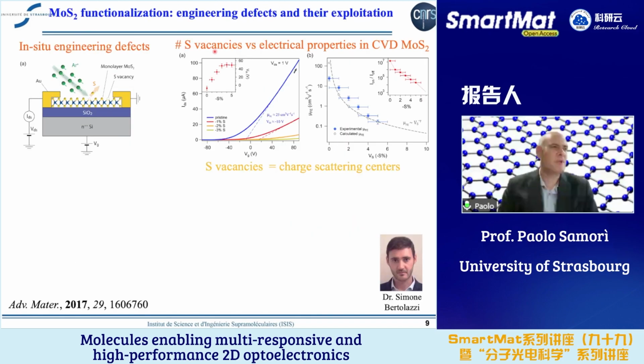Now, this is what we demonstrated in 2017 with Simone Bertolazzi in a study where we took simply molybdenum disulfide, which can be CVD, can be Scotch tape, and actually typically already in the pristine MoS2, every 10 by 10 nanometer, you have a point defect that is a sulfur vacancy. Well, this might not be enough. You might look for more defects, more vacancies, so by using some well-known approaches, we exploited the ion beam of the X-ray photoelectron spectroscopy, so of XPS. And so by irradiating with argon beam, we could generate more and more defects.